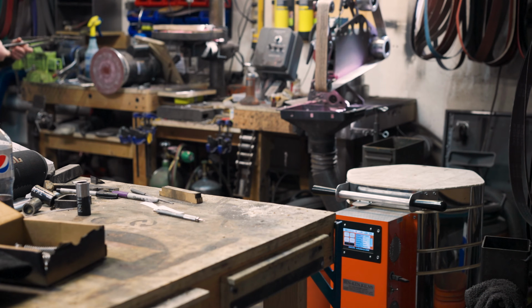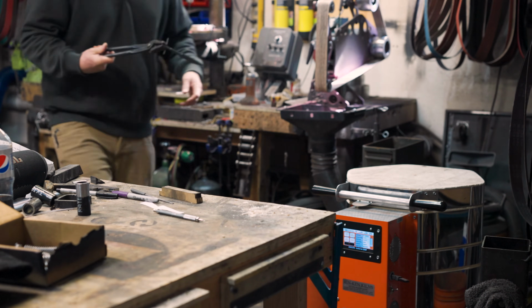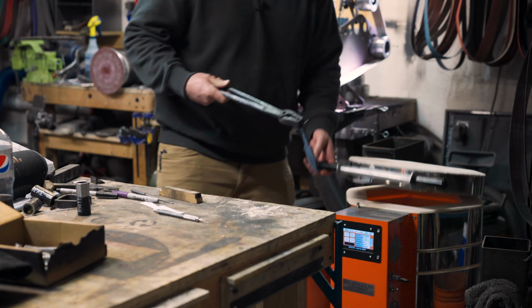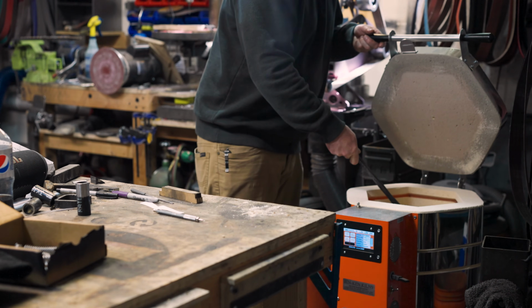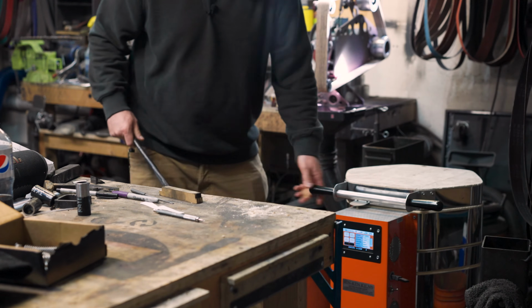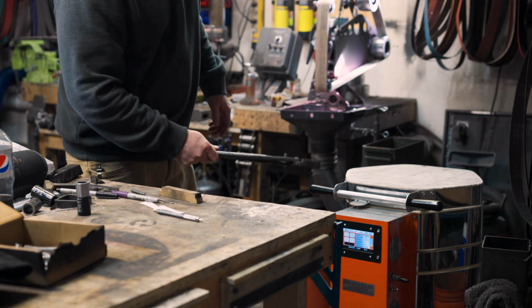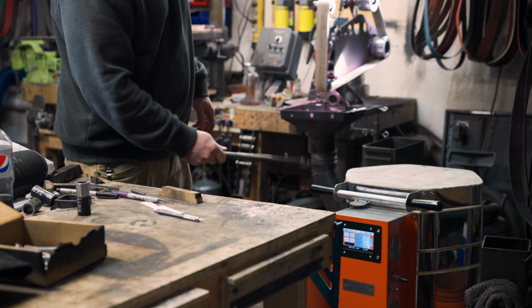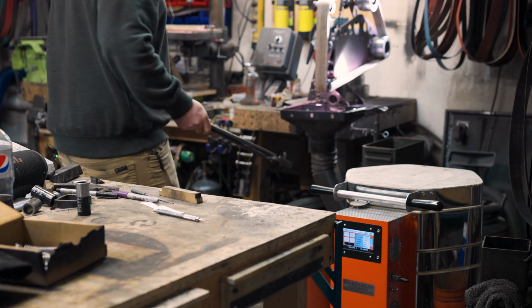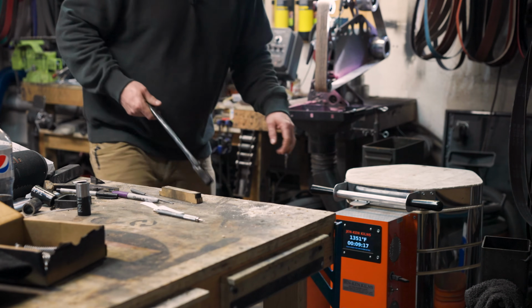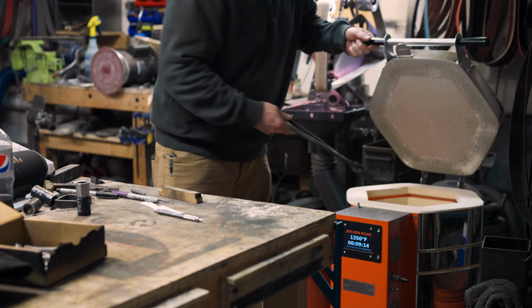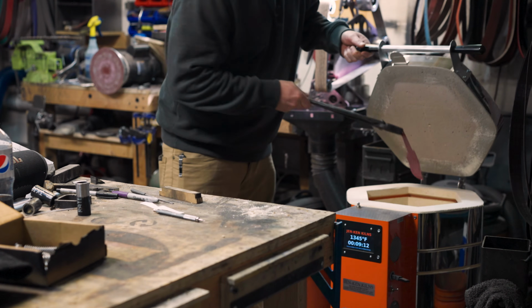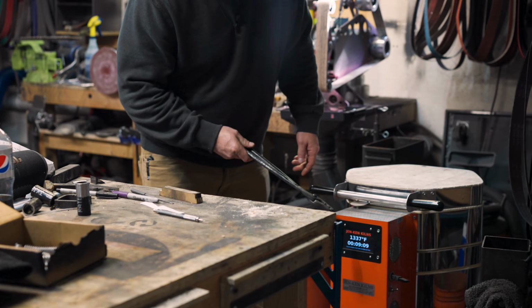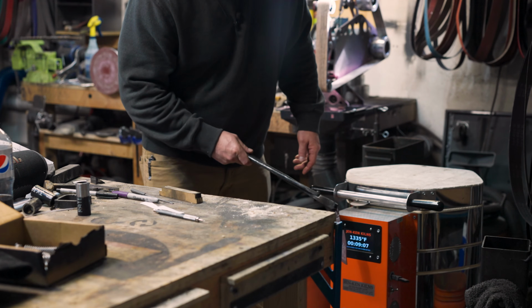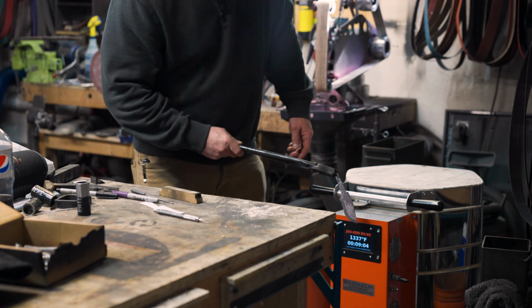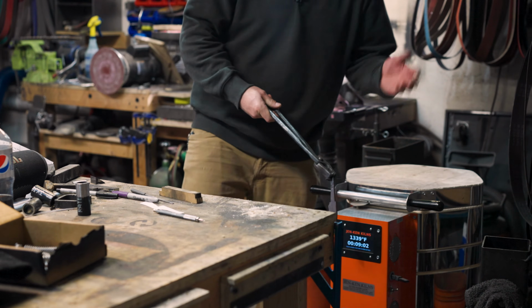So this is cooled to black, and we've got the 1350 schedule heating up. So we're going to pop that back in there, let it heat to 1350, give it a couple minutes to soak, and then back to the cooling rack. Here we are again, 1350 with a little bit of a soak. You can see that's barely got any color. You can almost call that purple if you want. Not really, but barely any color. So onto the cooling rack.